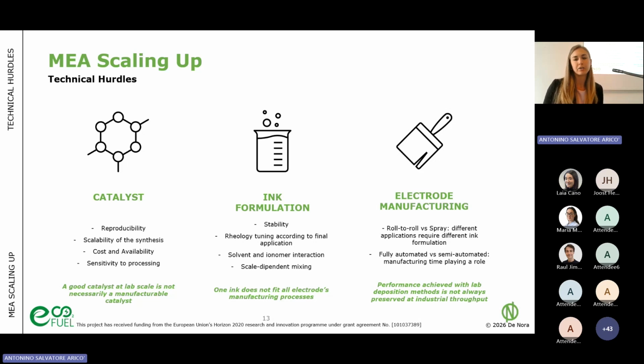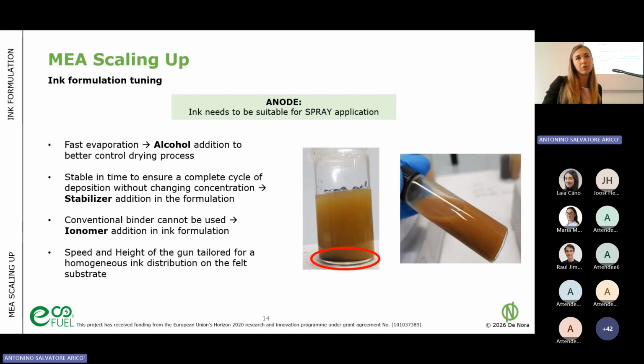And also the electrode manufacturing. We will see that we are using two different ways of manufacturing, the roll-to-roll in the case of the cathode and the spray coating in the case of the anode. And we will have a fully automated or a semi-automated production due to these differences. And we will see that the performances that are achieved at lab scale not always match what we are achieving at industrial scale. So, an example of what we did in the case of the anode ink.